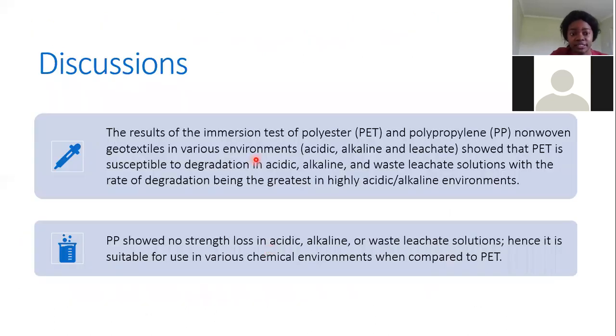So the discussion here is that polyester is more severe, it's more susceptible to degradation in all environments. And the greatest of these degradation took place in highly acidic or highly alkaline environments. While polypropylene, on the other hand, showed little or no strength loss in acidic, alkaline or waste leachates. So it can be used for various chemical environments, unlike polyester.